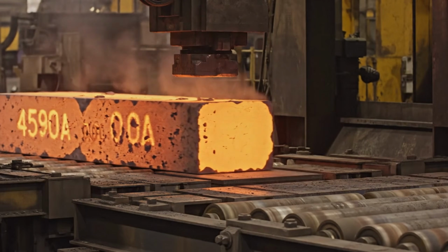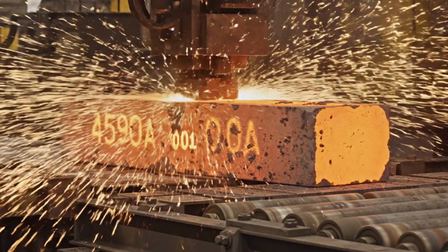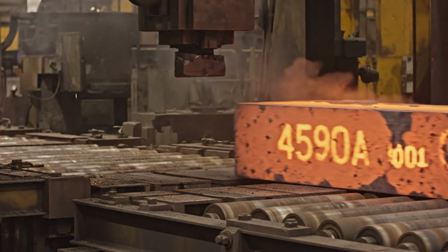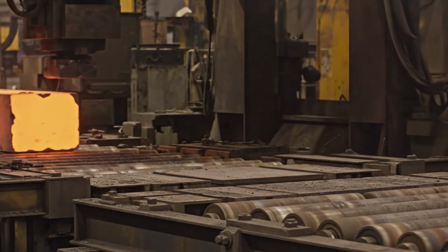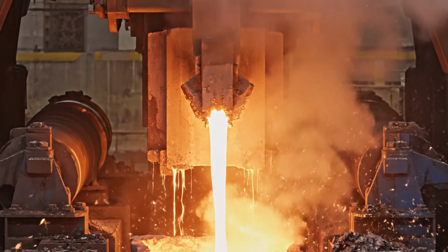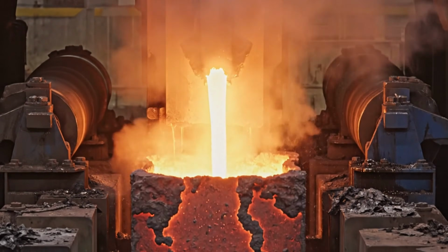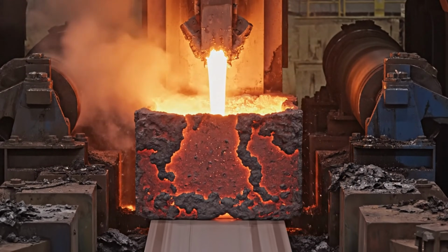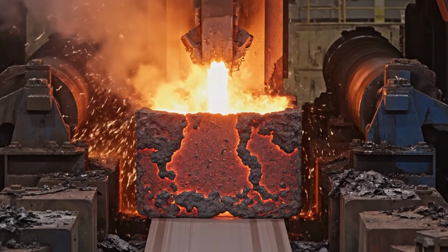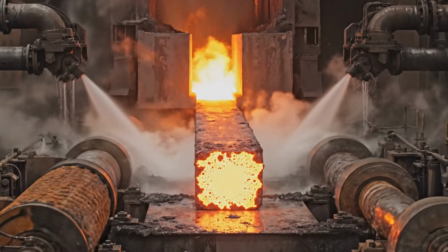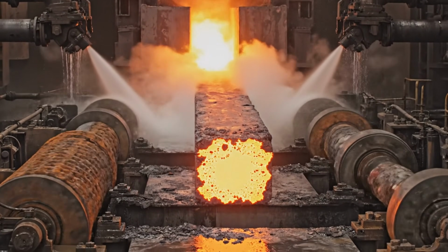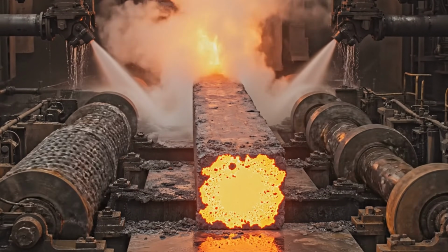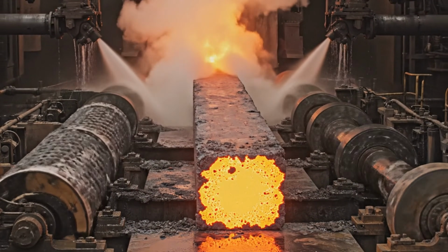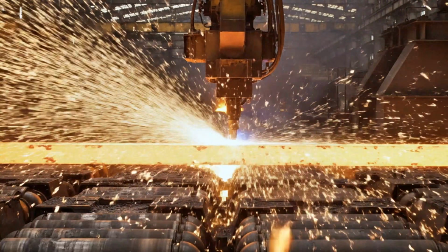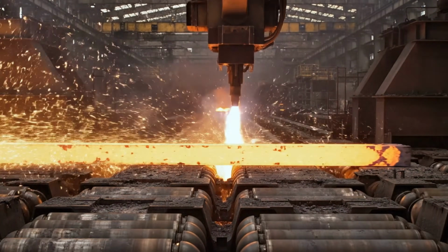Every billet is identified, so the plant can trace quality from melt to final product. Inside the mold, the outer skin solidifies first, while the core remains liquid. As it leaves the mold, the strand is solid outside and still liquid at the center. The continuous strand is cut into billets sized for the rolling mill.